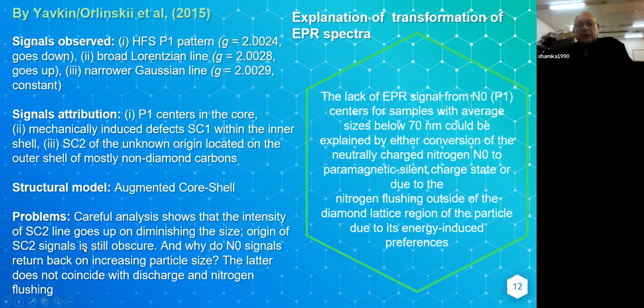Careful analysis shows the intensity of this narrow singlet line goes up on diminishing the size. Its origin is still obscure. And why do N0 signals return on increasing particle size? These facts don't coincide with this model. Their model of disappearance of the P1 signal is very simple. Below 70 nanometers, something happens with P1 centers, and they are converted to neutrally charged nitrogen N0, which is paramagnetically silent and cannot be observed by EPR.